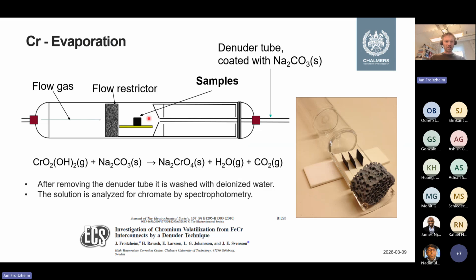Here's a little bit more detail of the setup we are using. So you have the gas coming in here, left-hand side. Here's our sample—this is now the tube that is in the tube furnace. And then downstream of the sample, you have this quartz tube, which I call a denuder tube, which is coated with sodium carbonate.